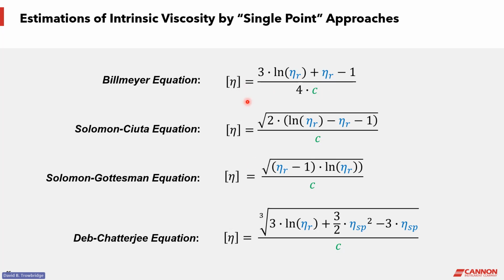But before you use these, it may be required in a method to use these, but if you use them with your own notion of saving amount of time and effort by using just one measurement, one solution, you should try to do the more rigorous analysis using the Huggins-Kraemer extrapolation and compare the results to each of these 4 calculations and see which one corresponds best, and that would be your selection going forward.